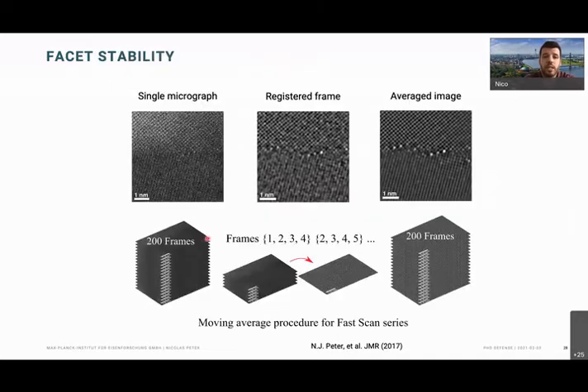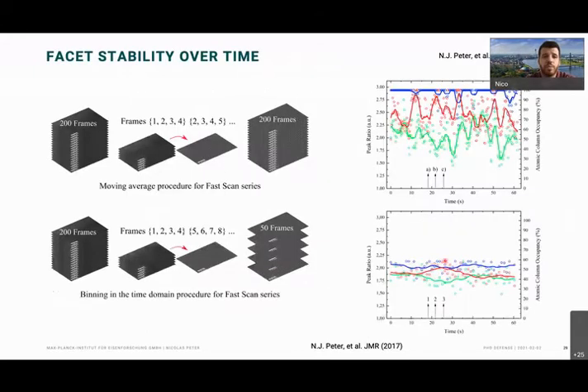How we did this in situ stuff, I would say, is we took 200 frames and then we did a moving average approach so that we take the first 4 images and then take image 2, 3, 4, 5, and then 3, 4, 5, 6. So in the end, we end up again with 200 frames. We can now also do a different approach in the time domain, saying that we take 4 images again, but then these 4 images form one image. And then the next 4 images form the second image. So we reduce basically from 200 frames to 50 frames.